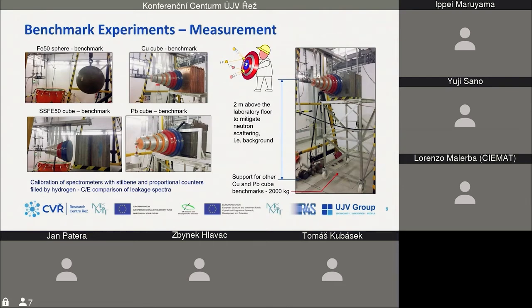For such measurement, it's important to mitigate the effect of reflected neutrons or reflected rays from the walls. So we standardly place such assemblies at a height of 2 meters above the floor. You can imagine it's not an easy task because the weight of such an assembly, as you see here, is about 2,000 kilograms. And the materials of the support should not affect our measurement, so it is made from duralumin, which is almost transparent to neutrons.